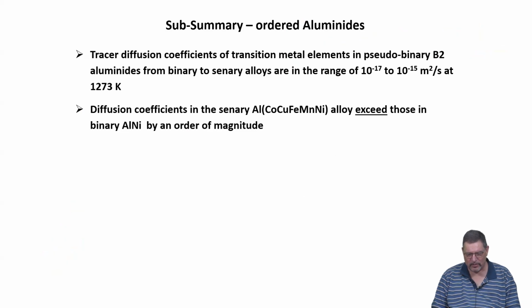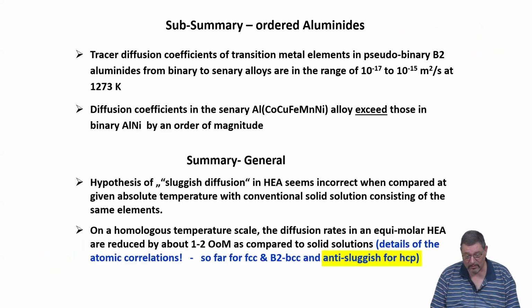So tracer diffusion coefficients of the transition metal elements in the pseudo-binary B2 aluminides are again in the range that is expected. In the 5-component system, it exceeds the diffusivity, and this means the hypothesis of sluggish diffusion has received another strong blow, because here we have anti-sluggish diffusion confirmed.